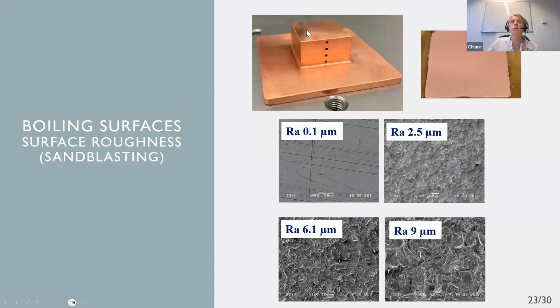Similarly, we wanted to also investigate the effect of varying surface roughness of the boiling surface. So we adopted a different machining technique. We used sandblasting to essentially enhance the surface roughness of our boiling surface. Here you can see 4 images from the SEM that show the 4 different surfaces corresponding to average surface roughness of 0.1 microns, 2.5, 6.1, and 9 microns. And this on the top right is a picture of the rough surface corresponding to 2.5. You can see already clearly the difference between this surface and the very smooth one.